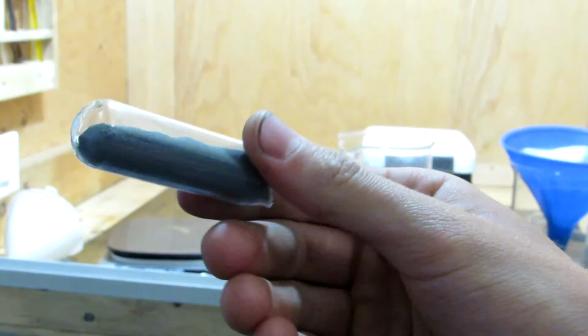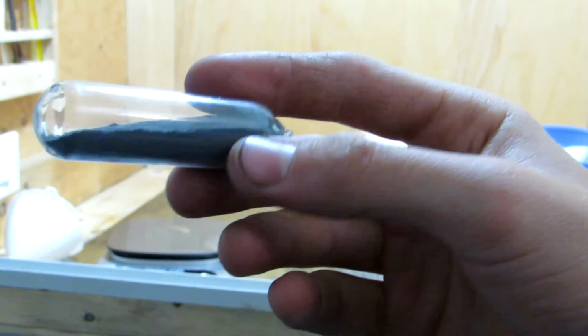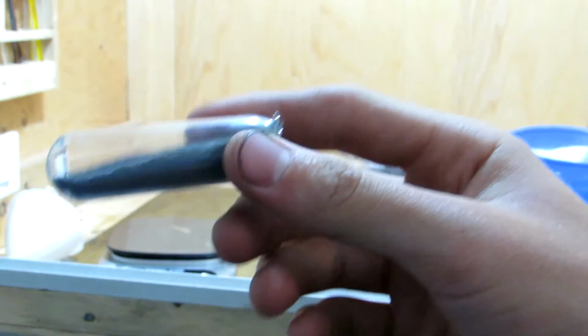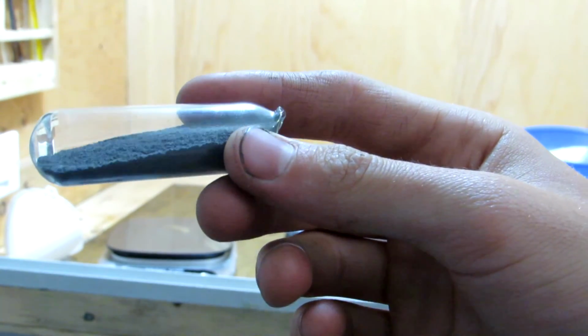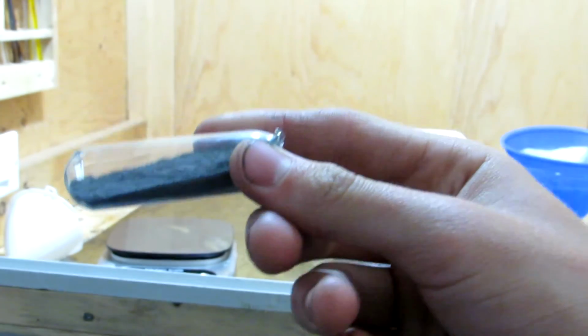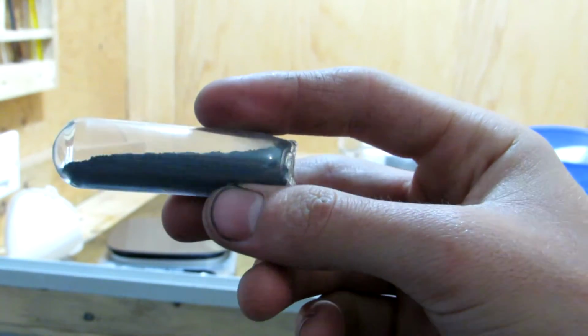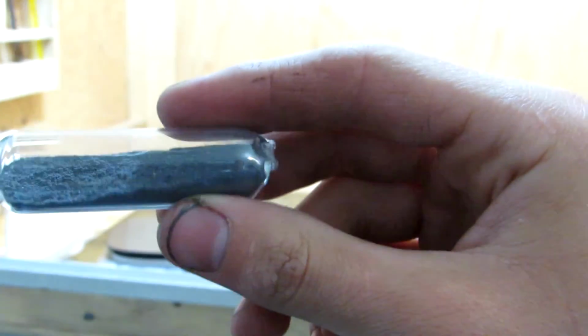Now, based on 100% yield, we would have expected 7.4 grams from the 10 grams of zirconium dioxide used, which corresponds to a 106% yield. This means that we definitely do have some impurities, and perhaps we have some unreacted zirconium dioxide, but this isn't the end of the world, and we definitely did make some zirconium.